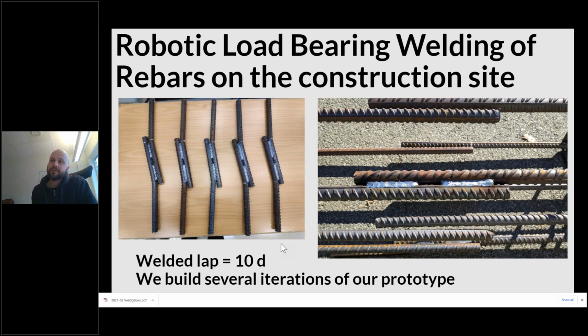But basically what we built during the 6 months is several iterations of this prototype, and we also tested it together with TWI and a local lab here. So what you see on the left-hand side is a few samples that we have welded. And you see they're bent a little bit, because of the testing process. And on the right-hand side, you see some tests that we have run with our prototype.